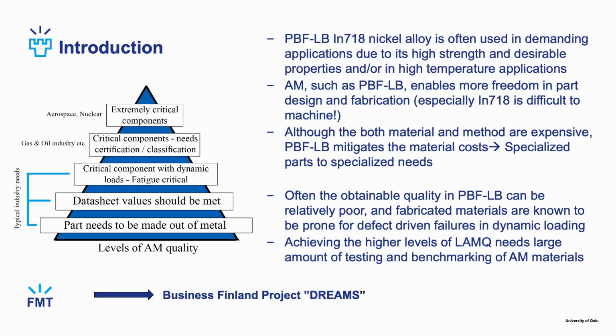But then we have this other issue: quite often the quality that we can get through powder bed fusion can be quite poor. The fabricated materials are known to be prone to defect-driven failures in dynamic loading. There are, for example, some papers that state there are over 100 process parameters that dictate the outcome of the fabrication itself. So we can consider these levels of AM quality